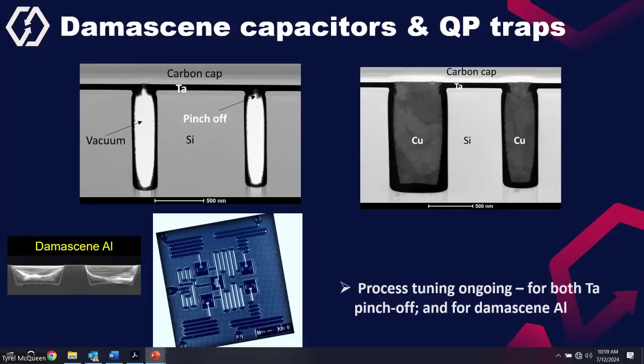So we create the trench in silicon and then we deposit the tantalum metal. So for the narrow CD, there is a pinch off here. And for the wider CD, when we deposit copper on top, the copper will be deposited there. So there is vacuum here basically. So this acts like a tantalum capacitor, and that can act like a quasi-particle trap because quasi-particle poisoning is one of the issues for qubit devices. So they can trap the quasi-particles. So we can use both of these on the same chip depending on the design. And one can act like Damascene capacitor, silicon-based Damascene capacitor with improved quality factors. Other can be used to trap the quasi-particles and improve the qubit coherence times.